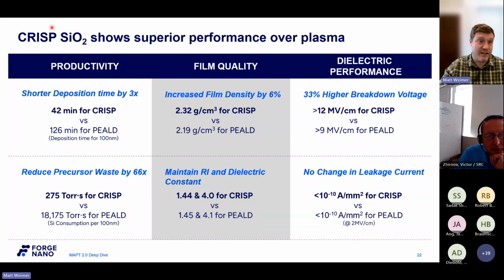So here is how our silica CRISP film compares with plasma enhanced ALD. I pulled this reference from the literature. I don't have a PE-ALD reactor on site, but this is a bit of a dated, I believe, ASM tool. Again, this was published. Similar precursors, both at 250C. So we're a bit faster to get to 100 nanometers, but we use much less precursor. They tell you what pressure they're using, what temperature, and we know how long they introduce it for and how long we introduce it for. So we're like 66 times less. Sometimes that matters a lot for people.